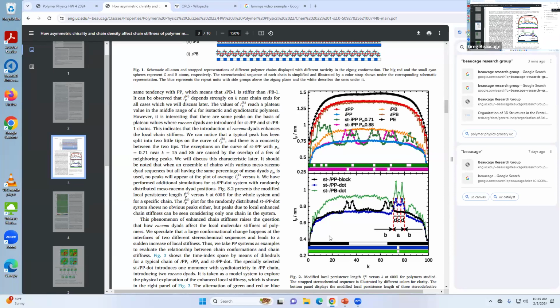or this RAFT polymerization that was in the other paper. Right? So you can use ionic polymerization, has no termination, then you can get blocks of one kind. Reaction's still going, you run out of monomer, then put in the other monomer and make the next, and then run out of that monomer and put back in the other monomer. So that's how you can make block copolymers like styrene, butadiene, styrene. That's SBS rubber. Tires are made of that. Basically, the tread compounds are SBR rubber. This kind of block copolymer.